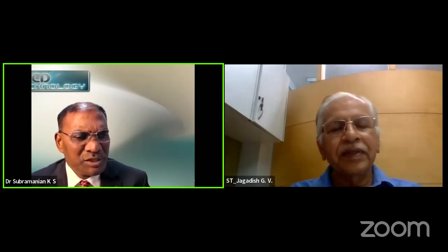Yes, sir. Last year, ICAR wanted to introduce this technology. Most of the ICAR centers are testing this nano zinc oxide, because it is very useful, including TNAU, which is one of the testing centers. And as I mentioned, 2 cautions have been given. One is the dose should be 1 gram per kilo of seed. Number 2, the size should be in the range of 50 to 60 nanometer, because zinc oxide can also be synthesized at an extremely small size, below 10 nanometer, which may be toxic. So these are the 2 cautions.